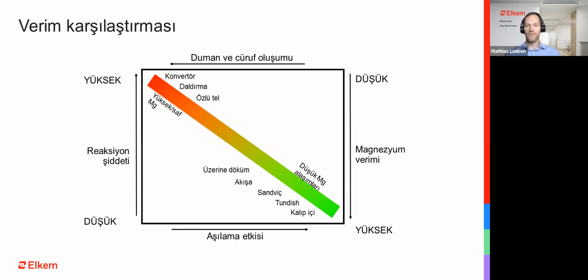Let's have a look at the efficiency comparison. Just a quick look at the upper left side. Treatments with high magnesium content or pure magnesium, like cored wire or the converter, will result in a violent reaction with lots of fumes and slag formation. We will have a low magnesium recovery and no inoculation effect at all.